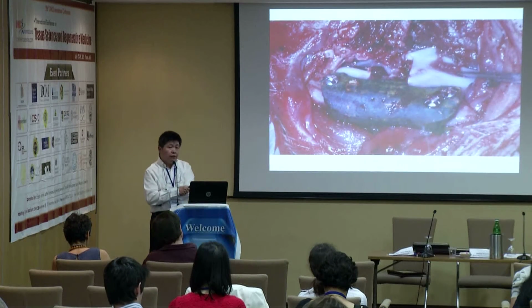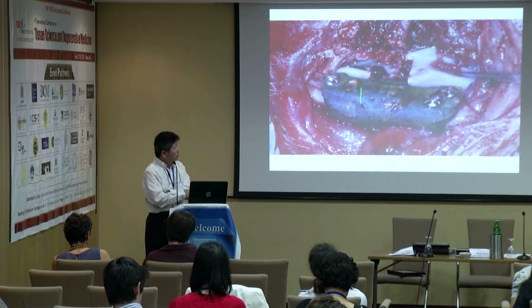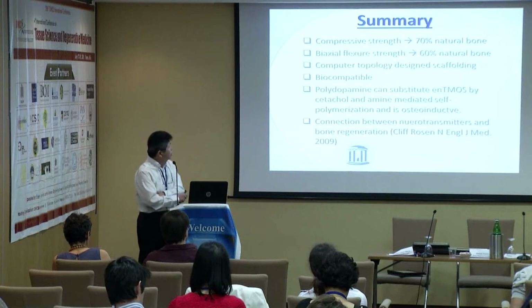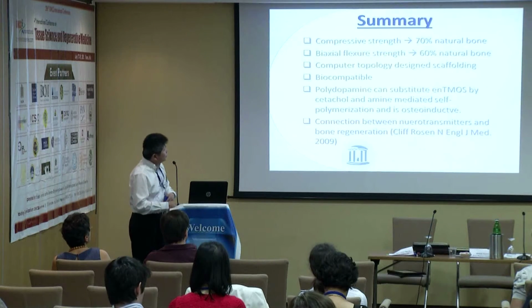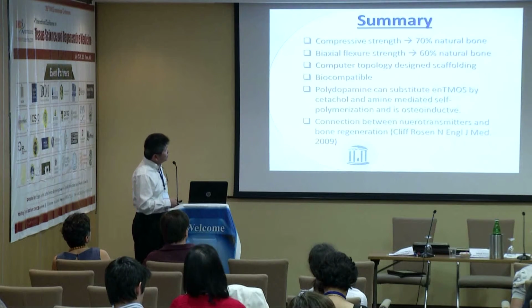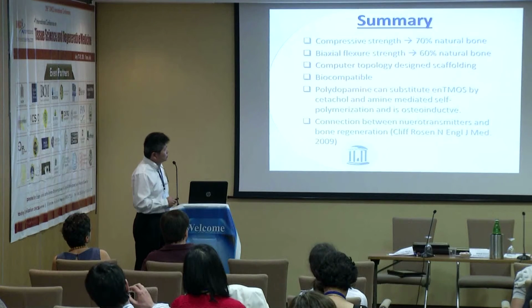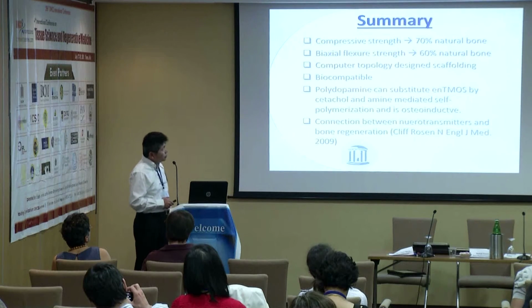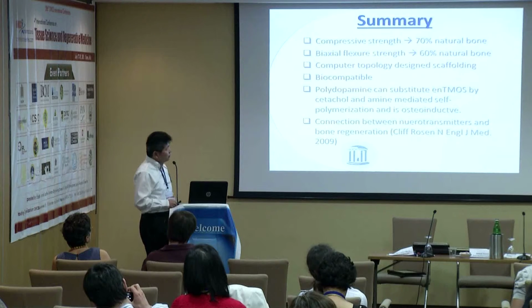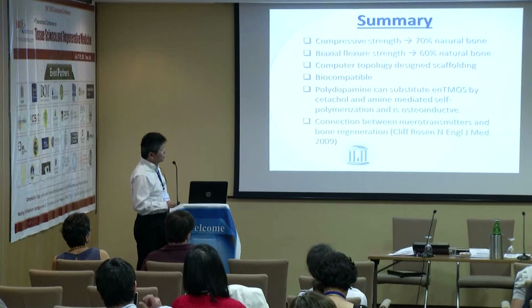I don't have final data for you because we just started this animal part about 2 months ago, and currently we have 3 to 5 animals running around. They are still intact in there. So to summarize very quickly, by adding this dopamine, we increase our compressive strength, so it's close to natural bone. It reaches about 70% of the compressive strength, and for the flexure strength, it reaches about 60% of natural bone.